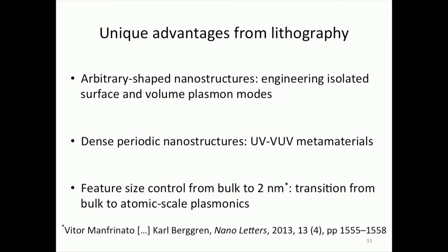Furthermore, you could, for example, pattern structures that are really close together, high density structures, in order to engineer UV and VUV metamaterials. And in this case, you will not only get an effective dielectric constant by putting structures close by, but by doing really high resolution patterning, you can locally modify the dielectric constant, adding another degree of freedom for metamaterials.